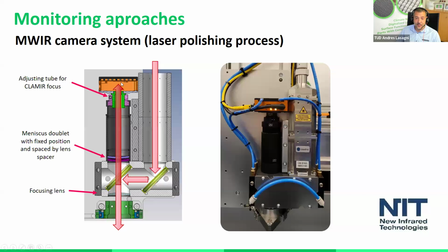And we have here then the infrared camera that is collecting information directly from the process zone. And here we can estimate a temperature and then correlate this temperature or even fluctuations in the signal to quality parameters from the surfaces we're creating. This is something where we are working. The idea is not just that with this equipment we will be able to say, okay, now the temperature is, let's say it's just a number, 1000 Kelvin. We will be able to say, okay, now you are getting a roughness of 0.5 micrometers. This is the ultimate target. But okay, this is what we have now, camera installed into our machine.